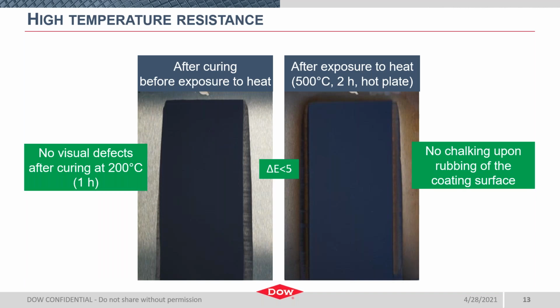Here's an example of what the 8016 based paint looks like before and after exposure to high temp. Both of these panels were cured at 200 C for an hour. The right panel was then exposed to that 500 C on a hot plate. Neither of the samples have visual defects or chalking, and the film integrity is excellent for both pre and post heat exposure. The sample exposed to 500 C on the right only shows slight discoloration, as mentioned on the previous slide with those numbers. It's just over that visually detectable limit.